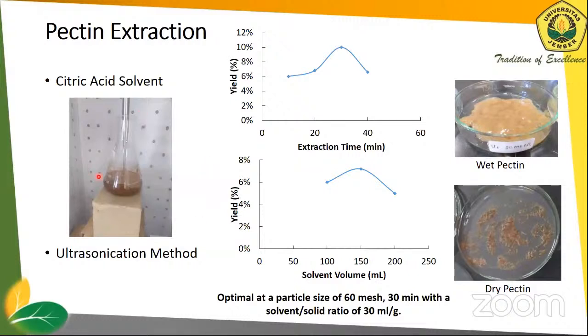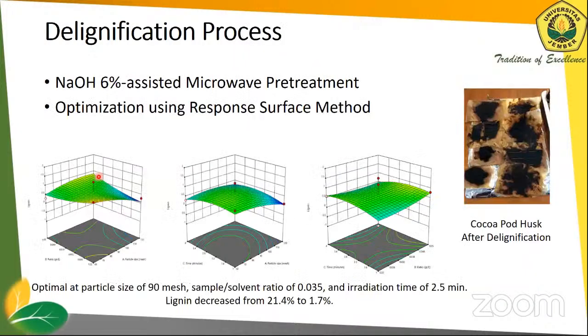we did the delignification process using microwave pretreatment with alkali. And here we can see that the optimum value for sample to solvent ratio is 0.035 and irradiation time of 2.5 minutes. Lignin was decreased significantly from 21 to around 2%. This is the cocoa pod husk after the delignification.